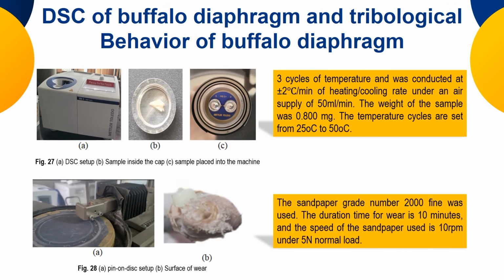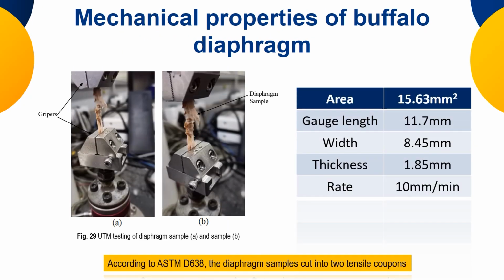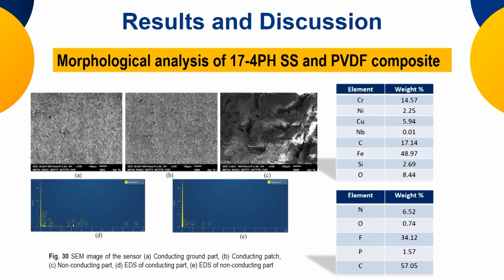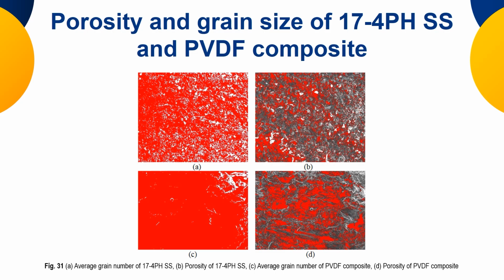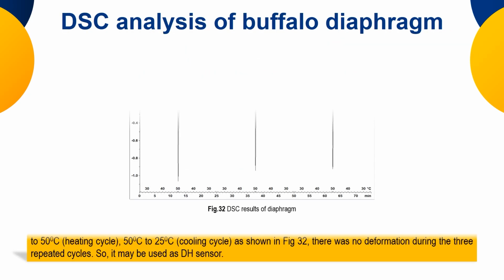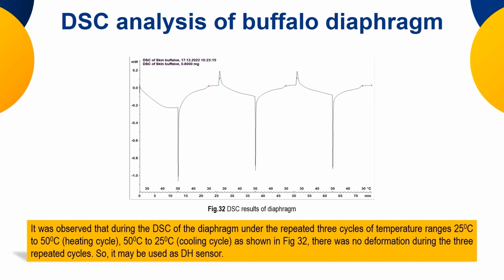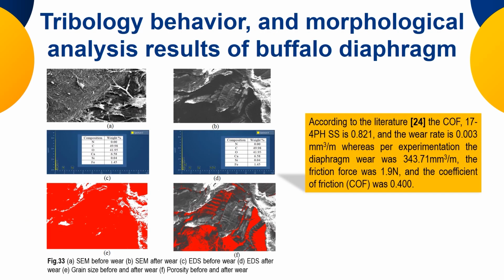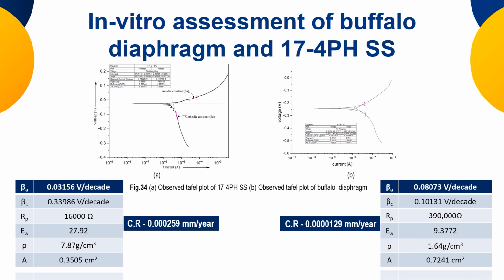Then for the actual fabrication, the DSC analysis, their wear behavior, their mechanical properties, as you can see on the screen, their morphological behavior, their EDS, their average grain size, porosity, these types of data that we learned in all our previous weeks are actually being implemented. And as you can see, the results of the DSC, their tribological behavior, and their in vitro behavior are very well within the limit. Like you can see, the corrosion rate comes out to be 0.000259 mm per year, and in case